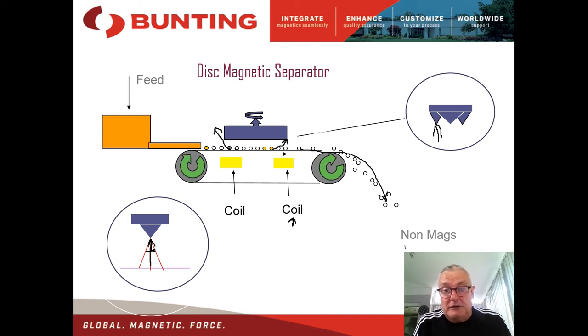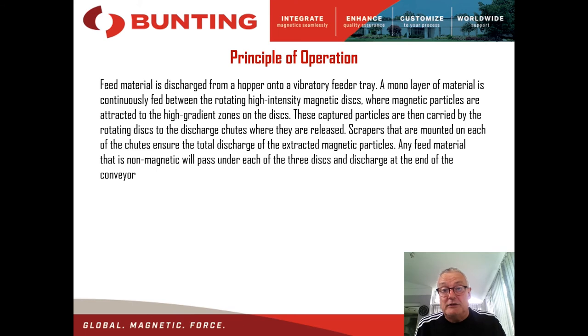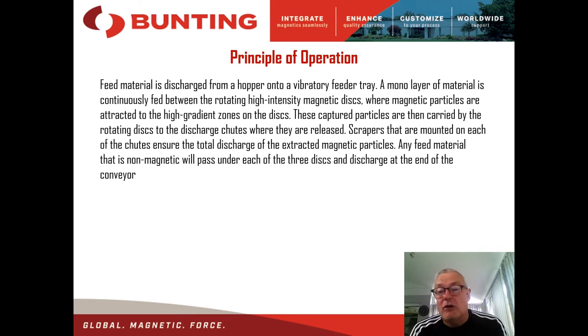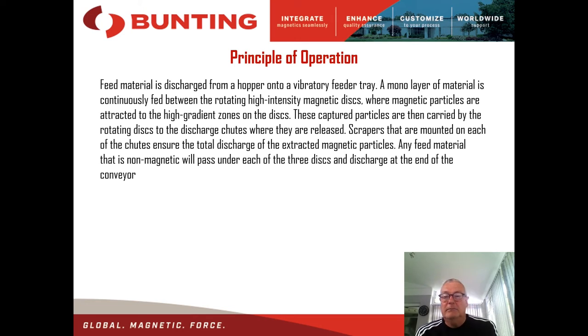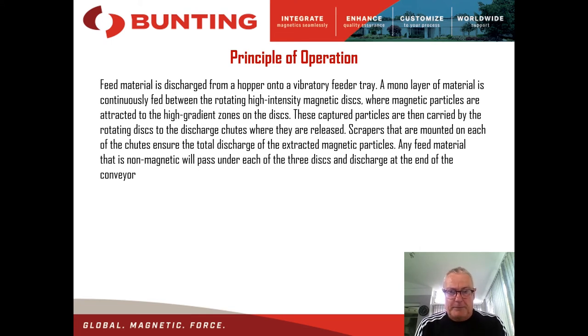To summarize the principle of operation: the feed material must be dry and free-flowing from a hopper onto a vibro feeder. It goes as a monolayer under a high-intensity magnetic disk. Magnetic particles are lifted off the belt, while non-magnetic particles pass through unaffected and come off the end of the belt. It's a continuous processing option for dry, free-flowing powders, often of complex makeup.